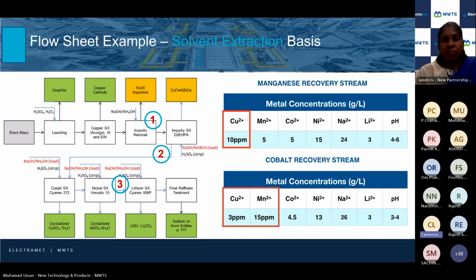So what that does is those small impurities are then transferred downstream to each of these other individual steps, where they now may be even more difficult to remove from that product stream versus if we could do it earlier. So the cobalt SX, the Cyanex 272, is the most common process in all the facilities trying to recover cobalt. And it is very good at sucking up manganese. So you can see that bottom right table there, there's still a significant amount of manganese in that product stream.